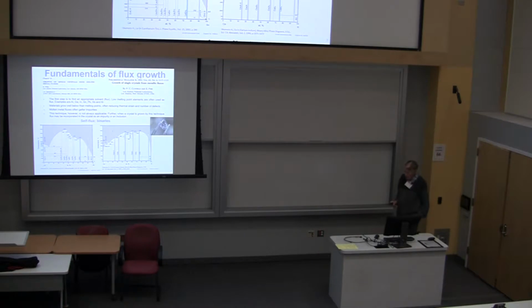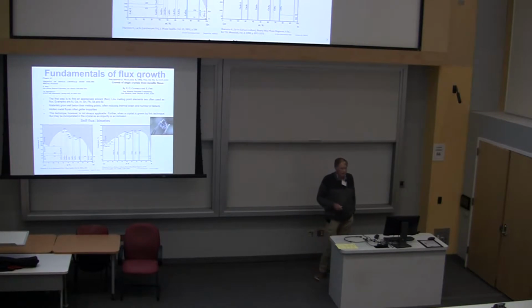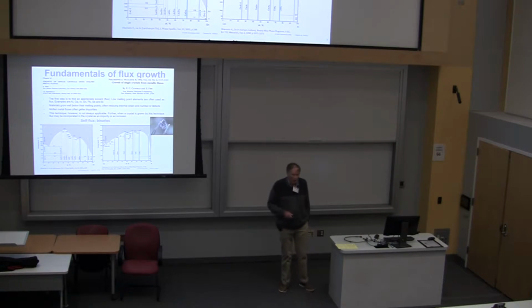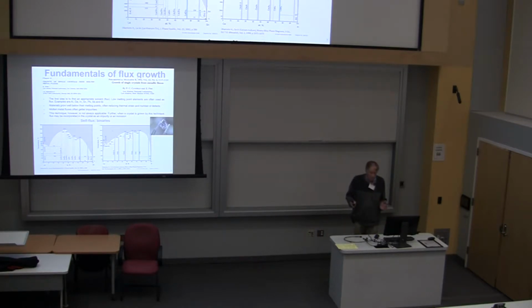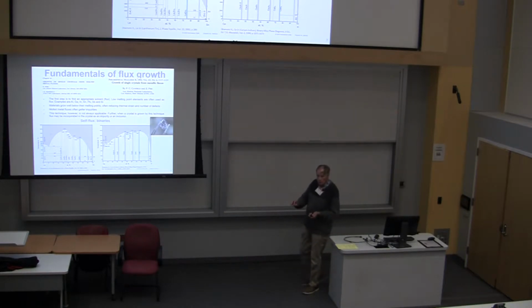about aluminum oxide. Even though it has what's called very good thermal shock resistance, meaning that you can heat it up quite fast and it won't break, there are sometimes when you have ingredients in your crucible that react as you're heating them up in such an exothermic way that they will break your crucible. An example of that is if you take, say, lanthanum metal with platinum. Try it sometime, put a little bit of platinum and lanthanum in a crucible, in an inert atmosphere or in a vacuum.